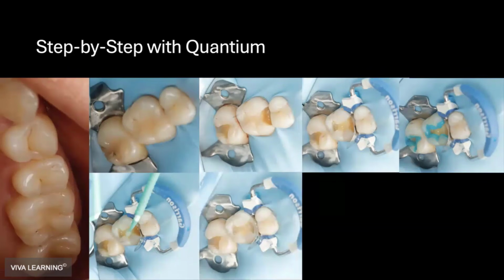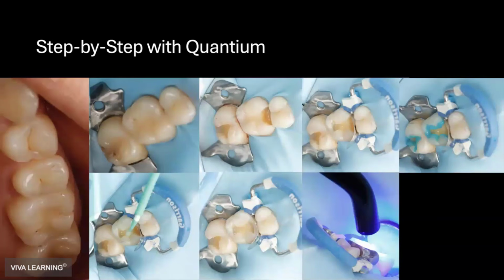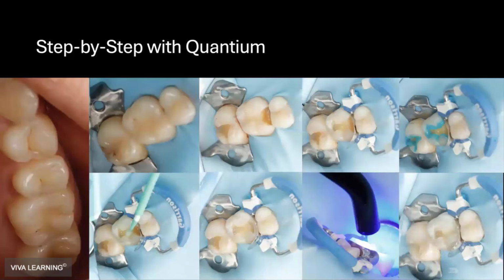Then build the marginal ridge. I use a splitter to kind of guide the resin to where I want it to go. Once I have the marginal ridge laid down, I cure for 20 seconds. Make sure that you have a pulsing curation on that curing light. Once I do that, I start building the anatomy in an anatomic way. If you remember the triangles we were doing, that's basically what I started doing here.